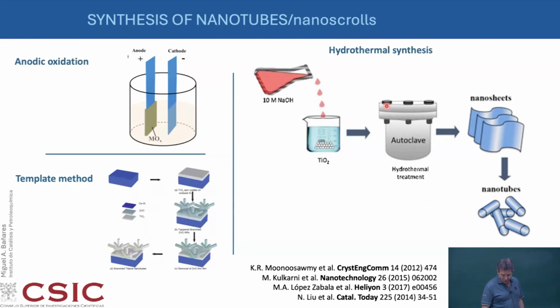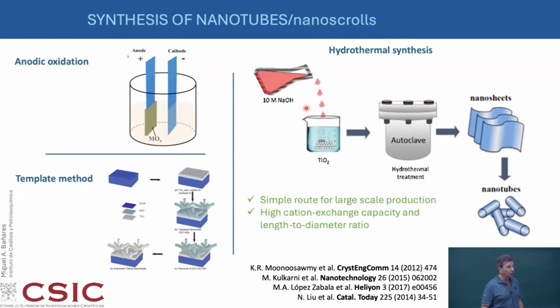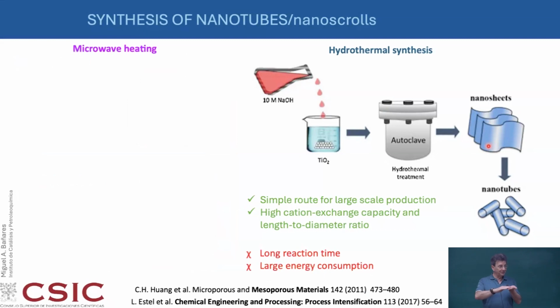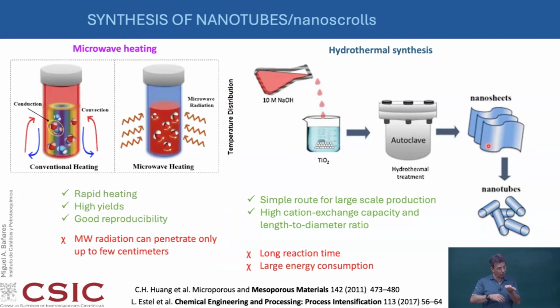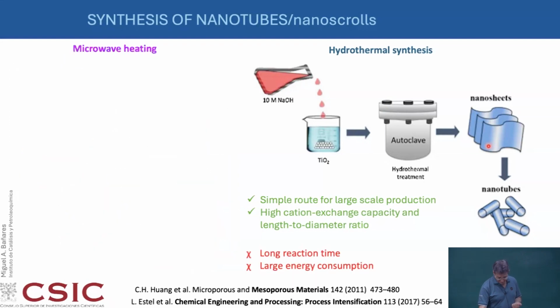Okay. The way you make titanium nanotubes is that usually you put titanium and sodium hydroxide, and you take it into a microwave or into an autoclave or into whatever. Basically, you heat until the sodium hydroxide reacts with the titanium into nanoplatelets, nanosheets, which is sodium titanate. So these are like platelets, like flat things of sodium titanate. And these sodium titanates are flat, and then when you wash them after the synthesis, what happens is that you can wash away the sodium and then it will scroll and make a roll. Sodium is away, what you have is titanium nanotube, well actually nanoscroll, because it's not like a tube, it's like rolling up something, but formally it's like that.